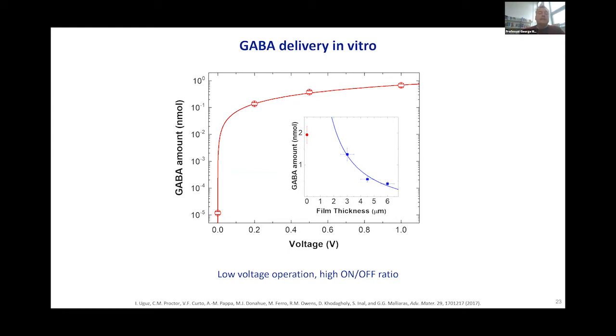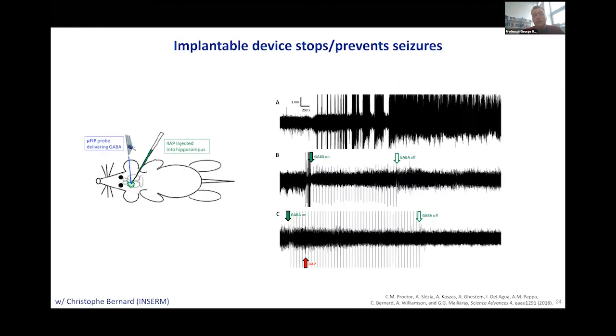So here we decided to use GABA, which is an innate transmitter, a neurotransmitter that is inherent in the nervous system, and it represents the brake signal that the brain gives to neurons to stop firing. And by applying just a very small potential, half a volt, you can dramatically increase the local concentration of GABA and achieve a therapeutic effect.